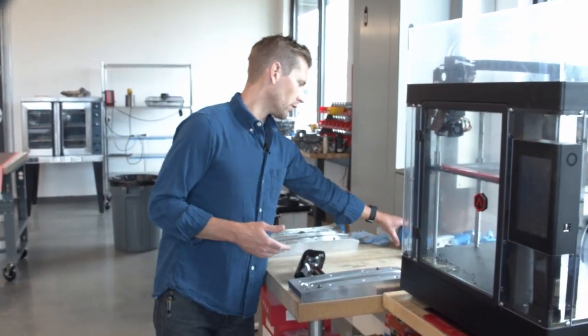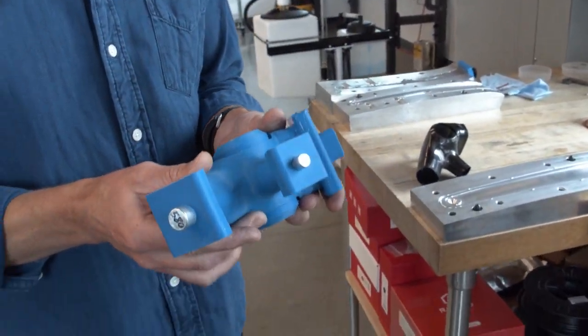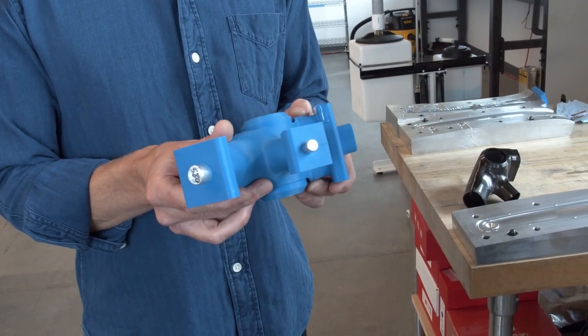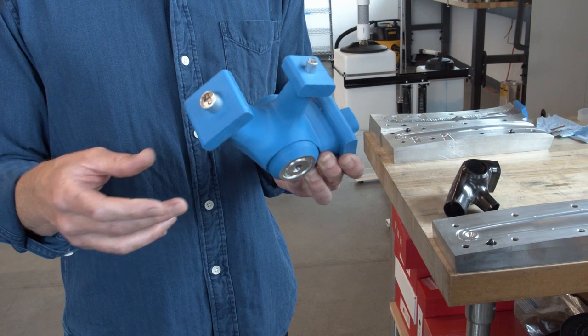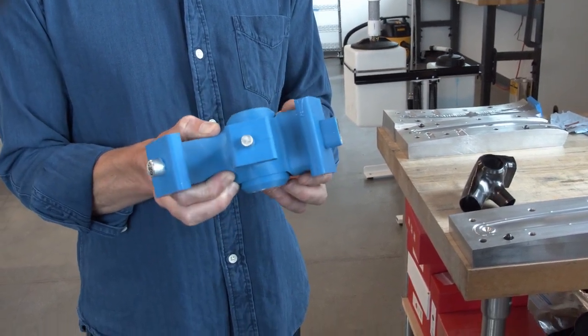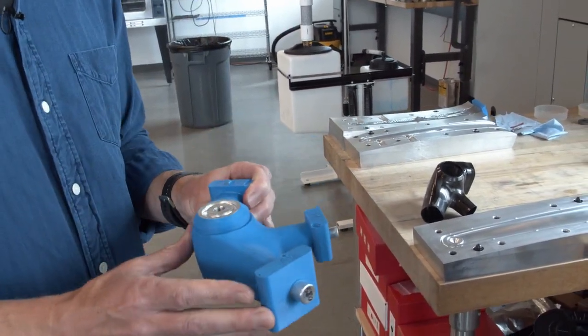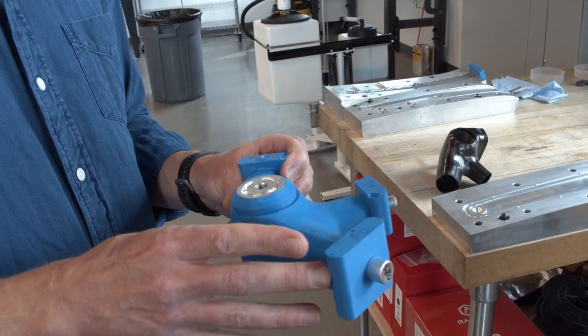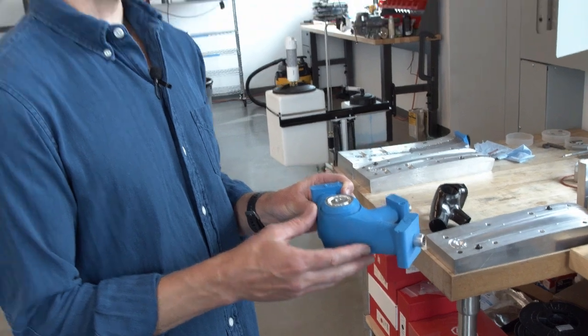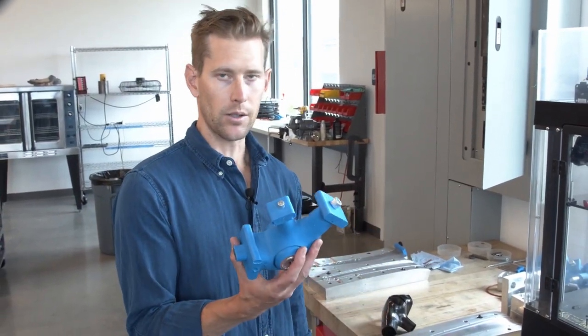We figured out a technology that we actually have a patent pending for, which is a modified way of molding carbon fiber called trapped rubber. And so the rubber refers to the silicone rubber of the internal mandrel. And then the trapped rubber is that this is contained in a mold. But to make these specific forms, what we actually do is we 3D print a mold to make this part.